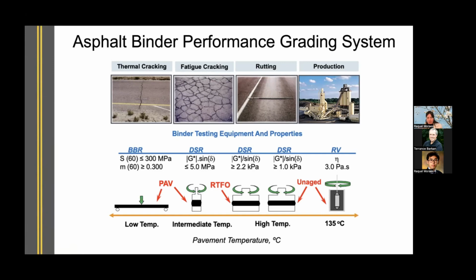For production temperature or production properties, we use a rotational viscometer at a temperature of 135 Celsius. For evaluation of rutting properties, we use a dynamic shear rheometer, considering the material at the original state and after a short-term aging in an oven. Then we evaluate fatigue cracking, also using a dynamic shear rheometer, but now the material is long-term aged. And then we evaluate thermal cracking, that is the behavior of the properties of the asphalt at lower temperatures, for which we use a bending beam rheometer, and the material is also long-term aged in an oven.